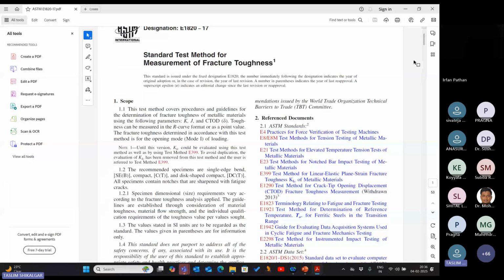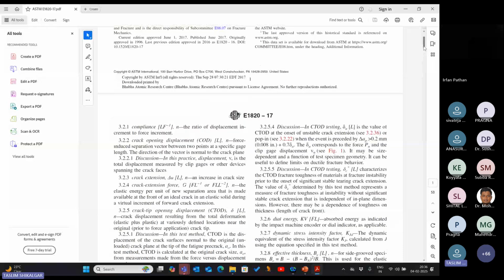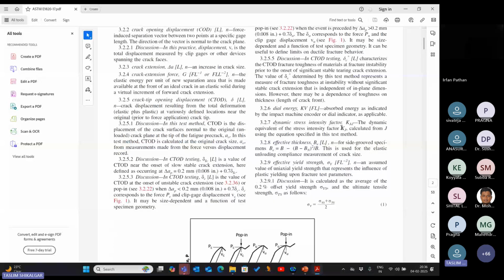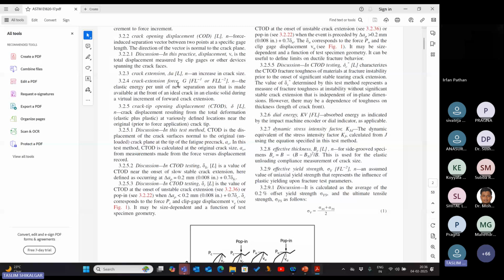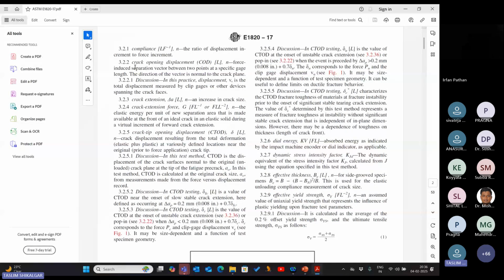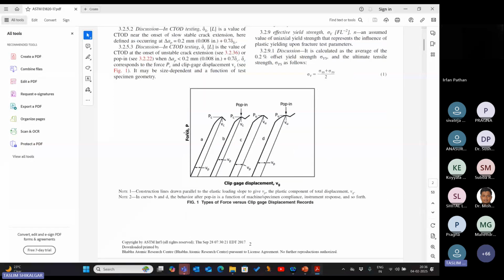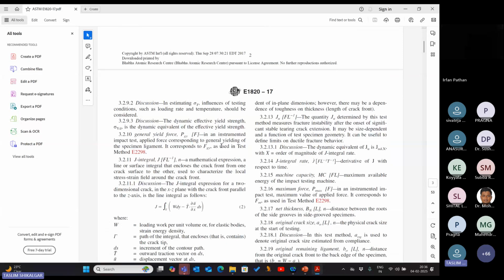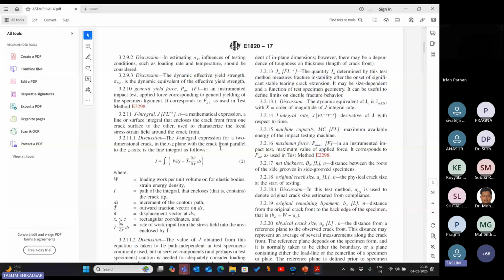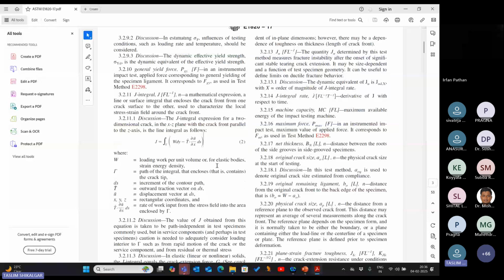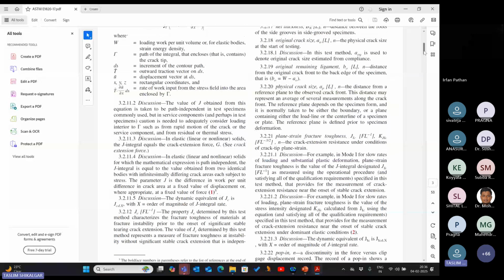If you go beyond this, it gives more definitions, like what is the crack extension, what is the force, what is the crack opening displacement, what is the CTOD, what is the J integral. Here you can see they plotted force versus clip gauge displacement. This is just load displacement data, but sometimes they use the crack mouth opening displacement. Here they also mention how we can calculate the J integral with the help of this ASTM standard.